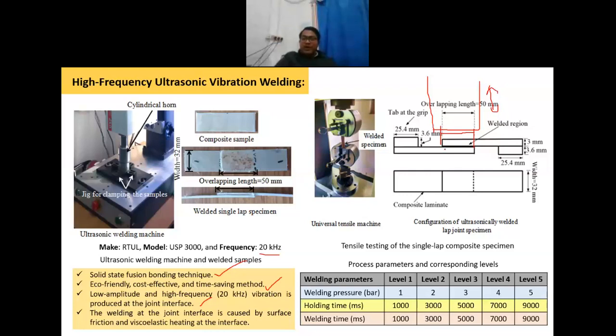Okay, so what will happen when it vibrates at ultrasonic frequency at the joint interface? There will be excessive heating. There will be a viscoelastic heating due to the friction, because it is vibrating at high frequency. Due to the surface friction, there will be viscoelastic heating, and due to that heating, the polymer will melt, and you apply pressure, you will get the joint. So this is how this process can be used for the joining of this type of composite materials.